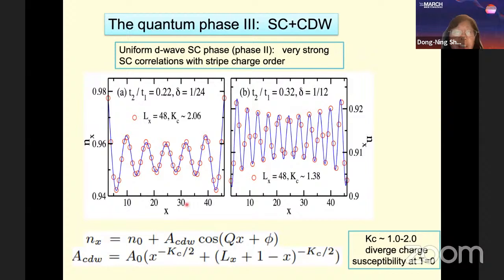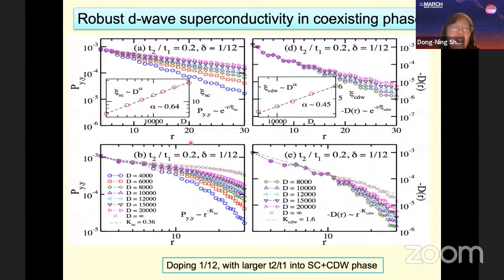Now we want to compare this picture with the third quantum phase, which has superconductivity coexisting with CDW. Those two figures show that for different doping levels, like when we double the doping, the stripe period is reduced to half, and within each stripe period we always have 2 electrons. Using the same parameters for this superconducting and CDW coexisting phase, we find that superconducting correlation still decays very slowly, following power law behavior with a small exponent much smaller than 1.